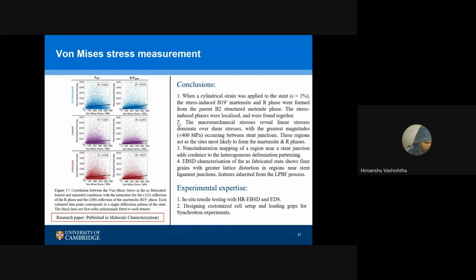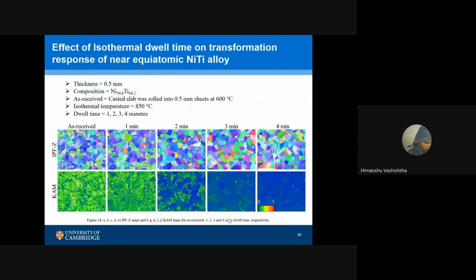To go through these additively manufactured cardiovascular stents is a pretty difficult experiment because we have customized a lot of things for this. So to simplify it, we took a nickel titanium plate, and that plate was rolled in the initial state, so a lot of dislocations were already there. We are heat treating it for 1 minute, 2 minutes, 3 minutes, 4 minutes, and that's the dwelling time, right?